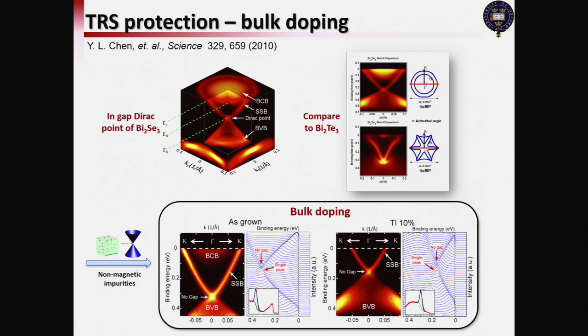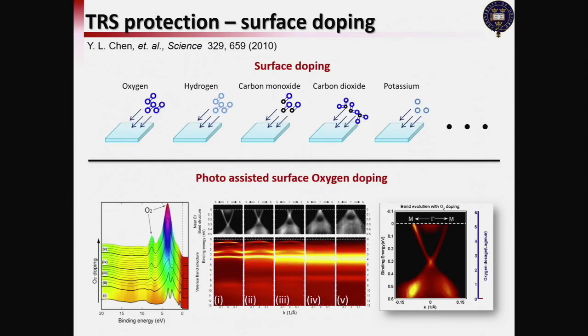So we checked that the doping was effective because you see the Fermi level change a lot. However, the Dirac point was robust, and the surface state was still there. So it seems that it's good. But then the question comes, this is a bulk doping, right? So what about the surface? So we try to screw up the surface by whatever atmosphere or gas we have in the chamber. We just dump all those things onto the surface and see what is going on.